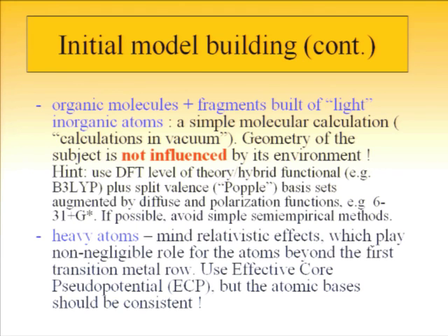It has some consequences, because if you take such a fragment and put it into an environment, I mean the structure, or the structural field, it will probably change the geometry slightly, and except for the case of rigid molecules, it is highly unlikely you get back the same molecule you inserted. Hint, use this level of theory because this is relatively fast and includes some correlation effects, preferably hybrid functionals. Those who are specialists know what I'm speaking about. Those who aren't, ask please a specialist, not me.